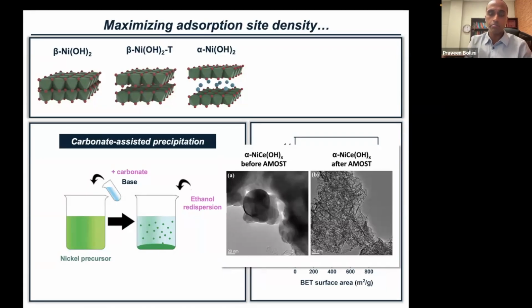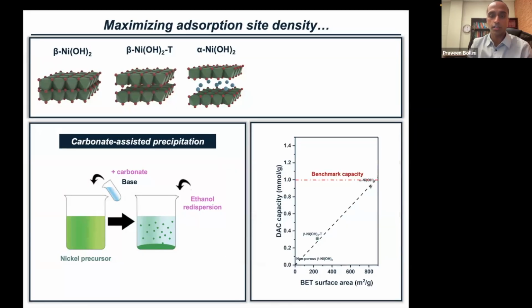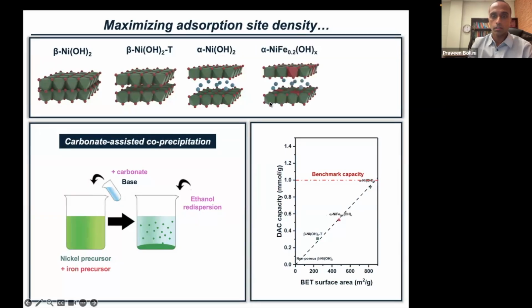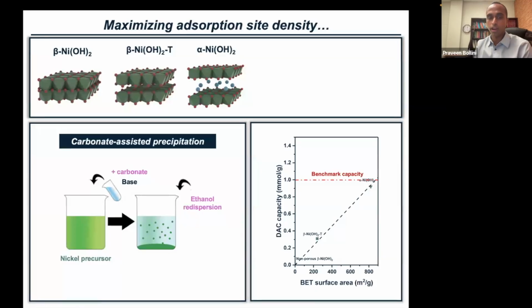So what you see here are TEM images on the right. The image on the left is the material before the aqueous organic solvent treatment, and the TEM image on the right corresponds to the material post aqueous organic solvent treatment. You clearly see the creation of this needle-like morphology at a few nanometers length scale, which is responsible for the high porosity that is created. And so we were able to create, in fact, the material that has the highest surface areas for any nickel hydroxide that we've seen reported in the literature. And as you can see, we're very close to the benchmark capacity because we have such a high surface area.